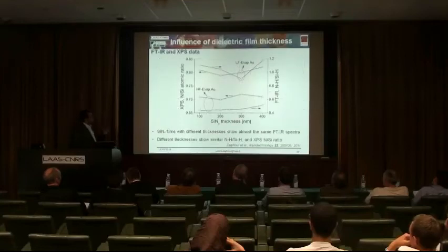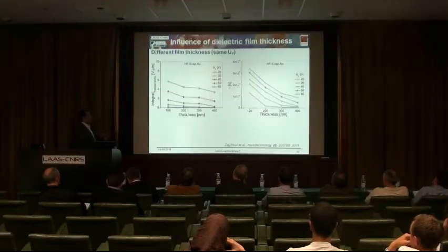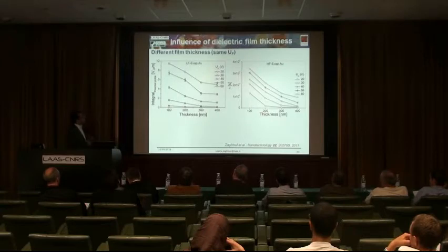We are going to use the same actuation voltage, which is almost the same case in MEMS switches. And what we found here is that increasing the thickness, at a specific voltage, will result in decreasing the injected charge density. This is a high frequency material, and it is even more clear in the case of the low frequency material. You can find that the slope is very high here.